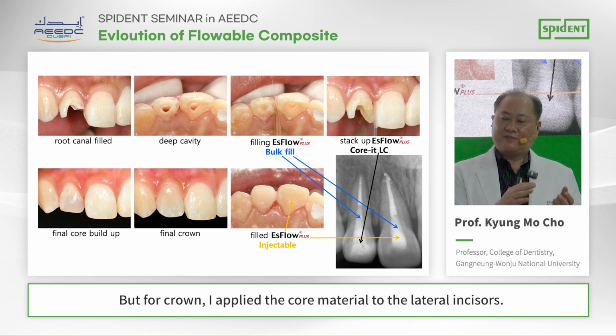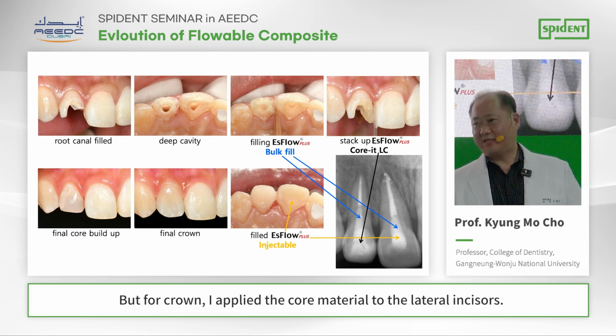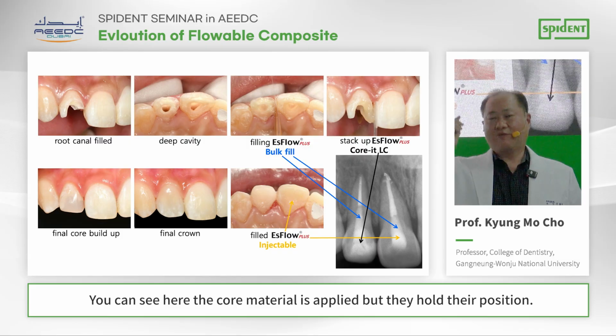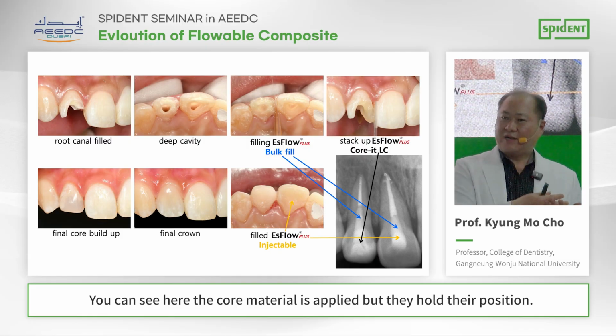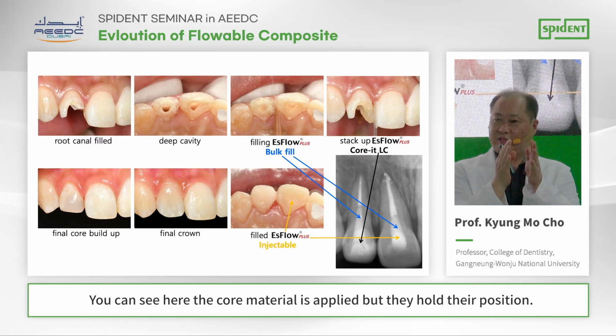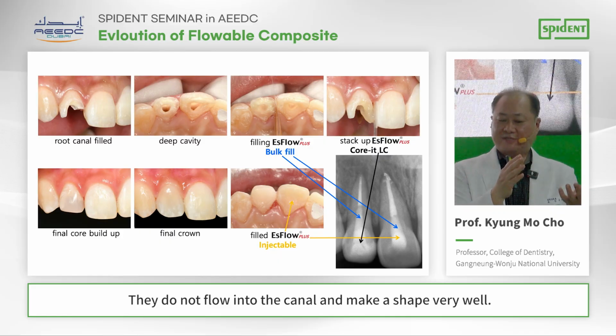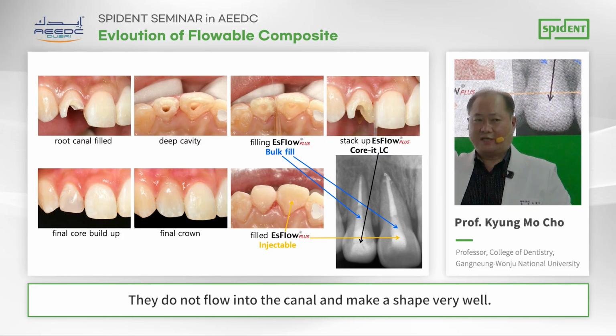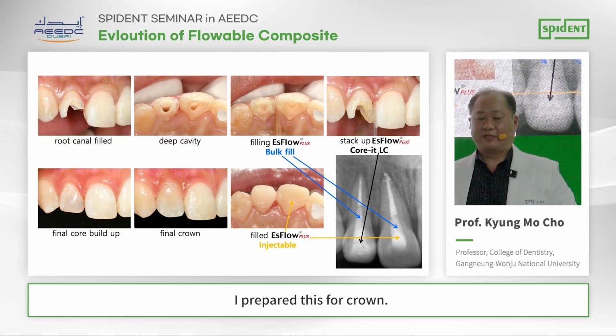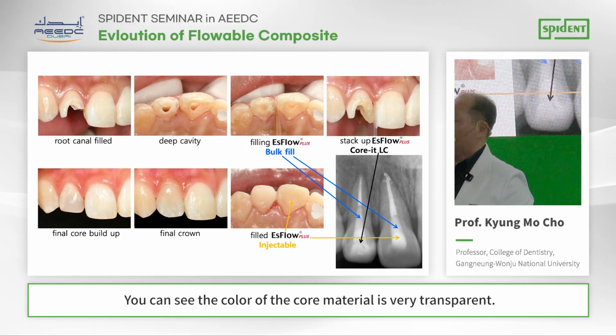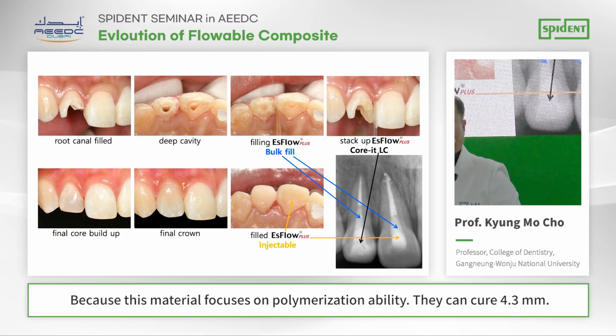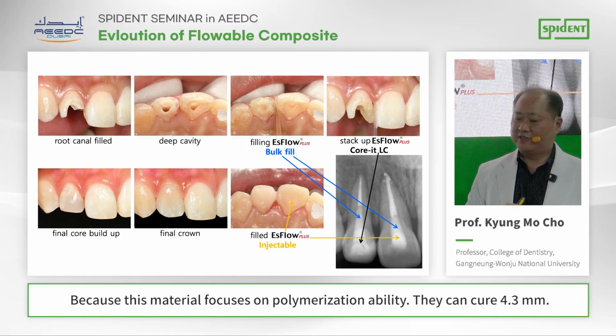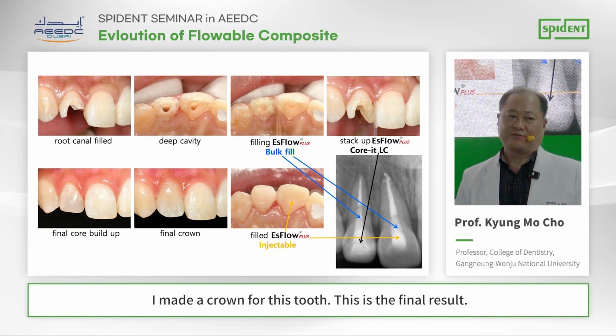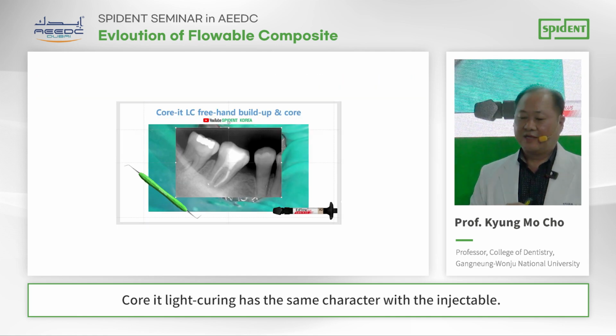But for the crown, I applied the core material to the lateral incisor. You can see here Core-it LC applied, but it holds its position, does not flow into the canal, and makes a shape very well. I prepared this for a crown. You can see the color of the core light curing is very transparent because this material is focused on polymerization ability. It can cure 4.3 millimeters. I made a crown for these teeth. This is the final result.